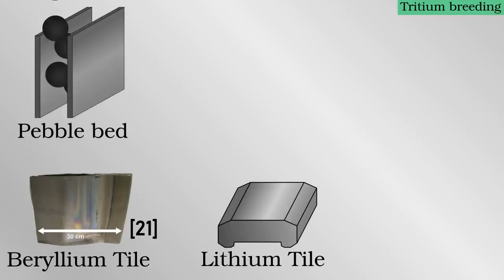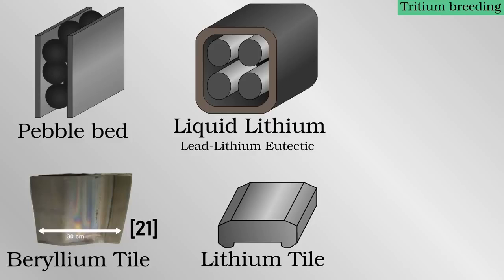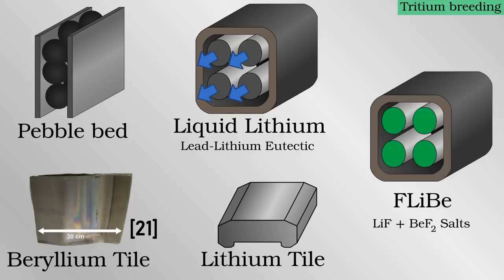The plan then would be to have beryllium just inside the first wall, probably in solid form as it is on JET, and some compound of lithium. The lithium could be formed into removable blocks or round pebbles. One promising idea is to use a lithium-lead eutectic, a mixture with a lower melting point than either of the metals on their own. With a low melting point, the liquid metals could be pumped through the blanket to simultaneously breed the tritium and take away some of the heat. Another good possibility is FLIBE, a mixture of lithium and beryllium salts with a relatively low melting point, which could also be pumped through the blanket. All of these approaches have their advantages and disadvantages, but none have yet been built or tested in reality.